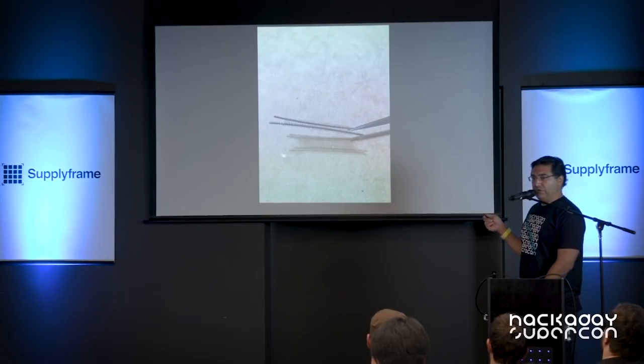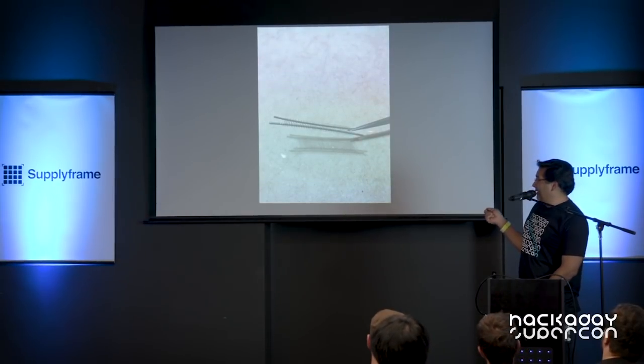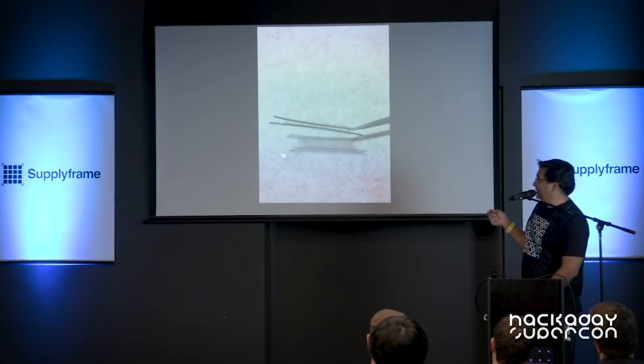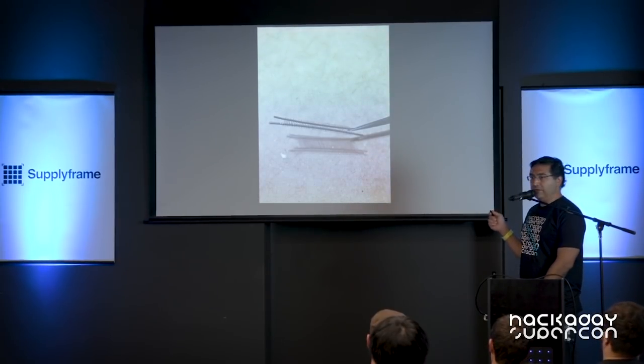They could not relieve the stress from it, and they were not stretching the material, which, of course, nickel being our primary material of use, is only work hardenable. There is no rolling process that can completely relieve stress and straighten properly with nickel. It must be stretched to straightness.